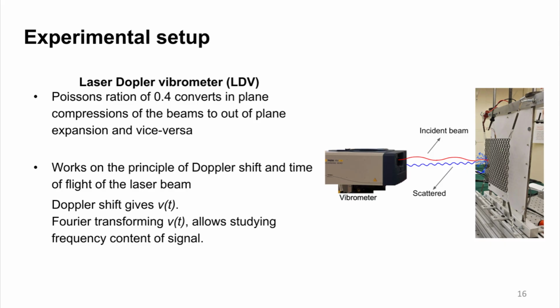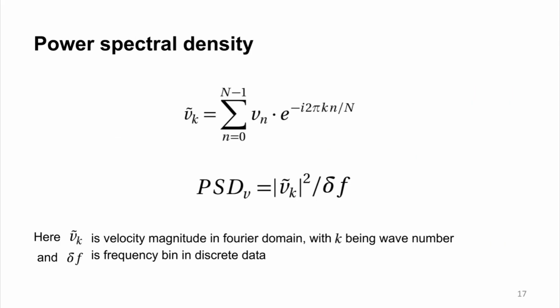The metamaterial I used, which is made from nylon 12, has a Poisson ratio of 0.4. So any vibrational sound waves that exist in plane, the compressions and expansions, get converted to respective compressions and expansions out of plane, and that helps me measure vibrations present in the metamaterial. And that is, as I said, how I get V of t data using Doppler shift from the laser Doppler vibrometer.